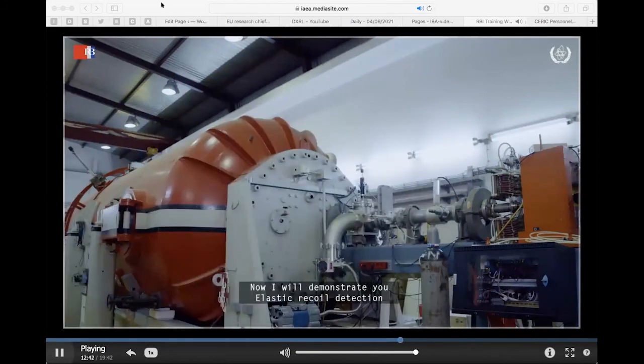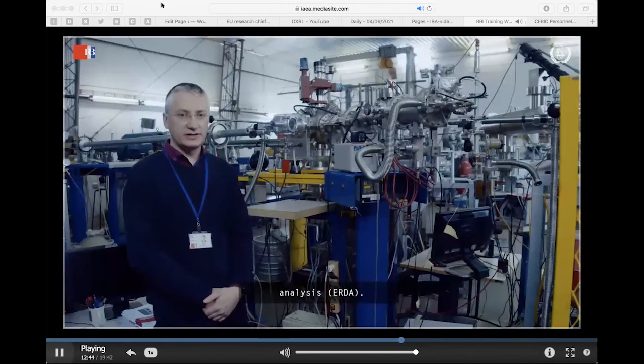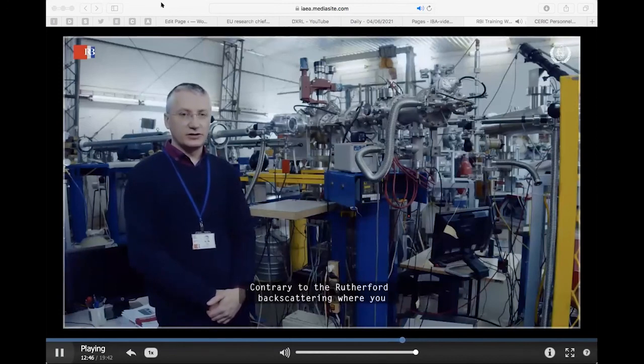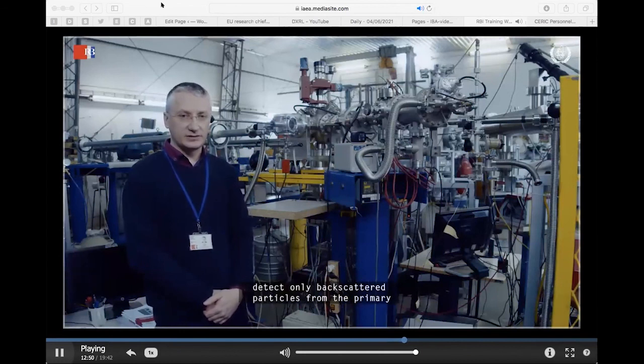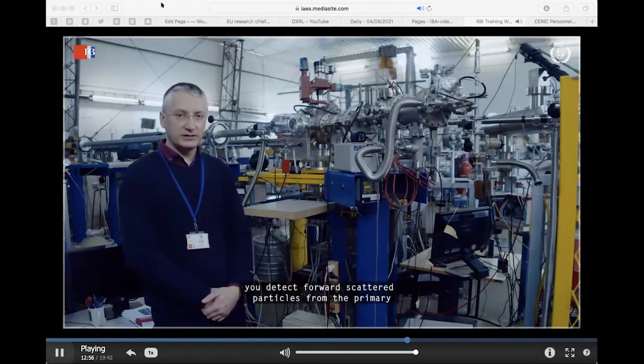Now, I will demonstrate to you elastic recoil detection analysis, ERD. Contrary to Rutherford backscattering, where you detect only backscattered particles from the primary ion beam, here, in elastic recoil detection analysis, you detect forward scattered particles from the primary ion beam and also recoiled particles which are inside of the target.